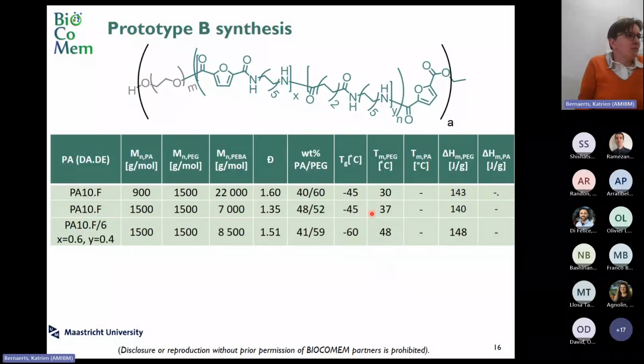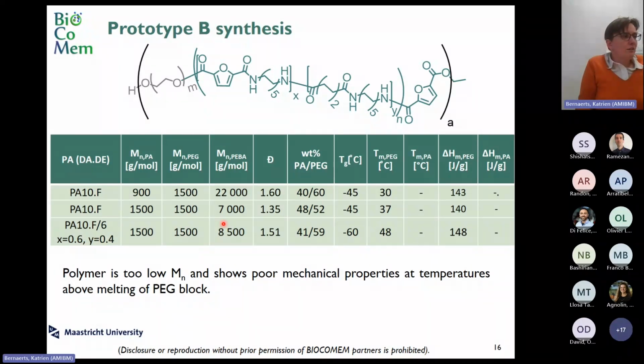In the next slide, you see some typical characteristics of the PEBAs we made. We varied the composition, we made pure homopolymers and we made copolymers. We also have the observation that the molecular weight of the PEBA is relatively low. We know that we need at least a molecular weight of 40,000, but unfortunately, with this chemistry, we couldn't go to much higher molecular weight than 22,000. This also results in poor mechanical properties.